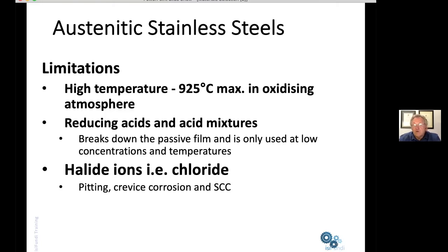Stress corrosion cracking happens when you have both stress and corrosion, and generally at higher temperatures. A rule of thumb for stress corrosion cracking of these materials is the 50-50 rule. If you've got 50 parts per million chloride and 50 degrees C, you're likely to get stress cracking.